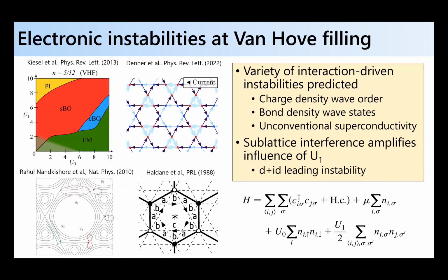And so there's been a lot of theoretical work exploring unusual physics that can happen if you can tune the filling towards this P-type Van Hove singularity, okay? There are a number of different interaction-driven instabilities, which range from various flavors of charge density wave order to unconventional superconductivity and bond density wave states. I'll call out two of the interesting predictions. If you can imagine having a bond density wave order that modulates hopping across the kagome network, one can imagine a so-called flux phase, or as I'll call it, orbital antiferromagnetic phase, in which you realize antiferromagnetism in the absence of local spins.